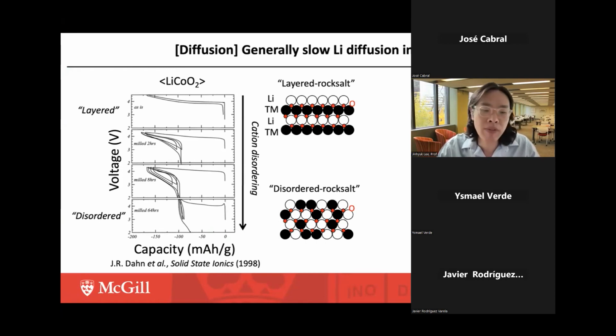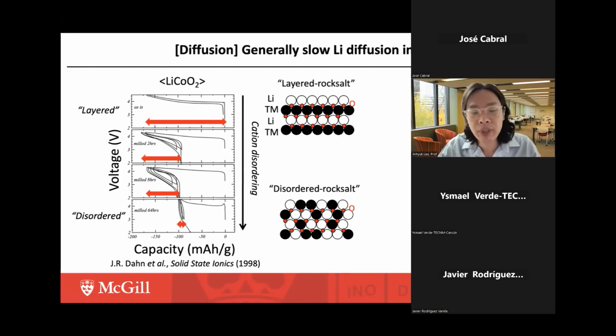Now in this type of profile, the x-axis is the capacity, the amount of lithium ion and electron this material can reversibly store and release, and the y-axis is the voltage. If you look at this voltage curve, we can see that the charge storage capacity of lithium cobalt oxide dramatically decreases as the structure changes from the layered to the disordered rocksalt structure.